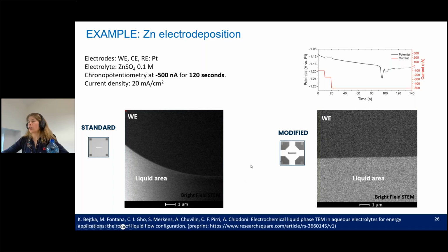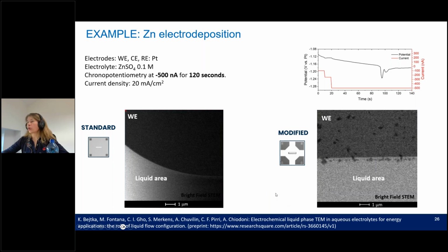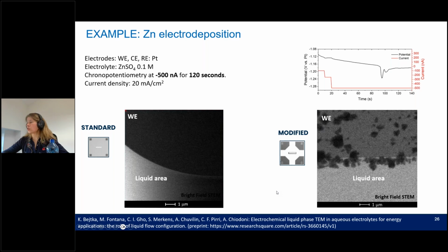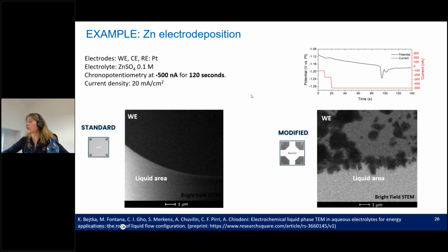And when we use the modified, so the improved flow configuration cell, and apply this chronopotentiometry, we observe nucleation and growth of zinc nanostructure, so the electrodeposition was performed. And we have run this for a little bit longer times because we have run for 120 seconds and added these 2 initial steps to go to the current of interest in a slow manner. And we observed that actually for all this time, the cell stayed filled with liquid, and the gas production, which possibly was still a competing reaction there, did not disturb the deposition.